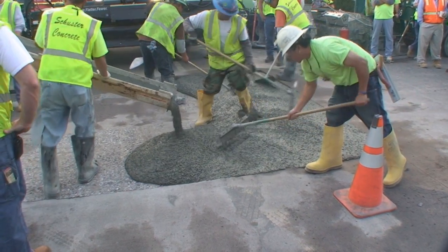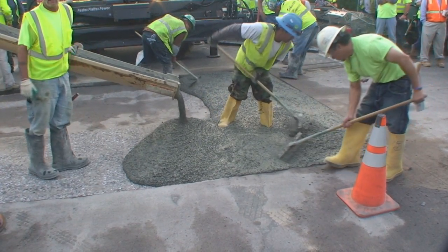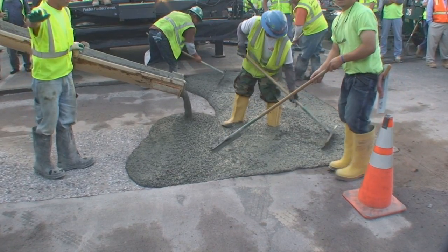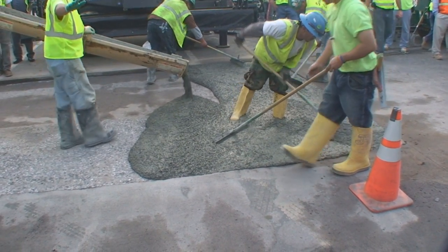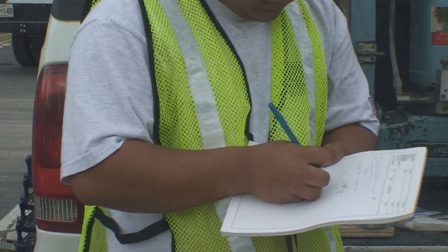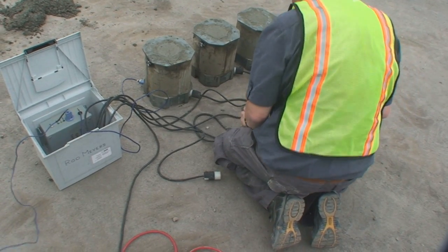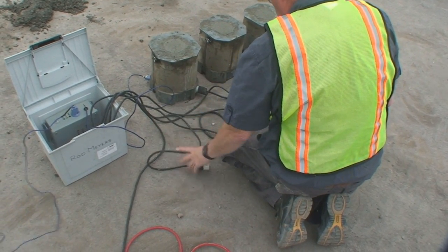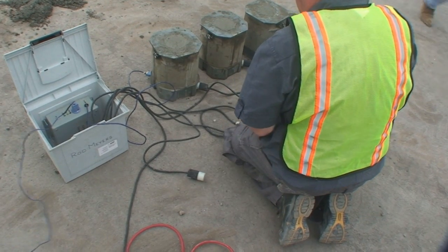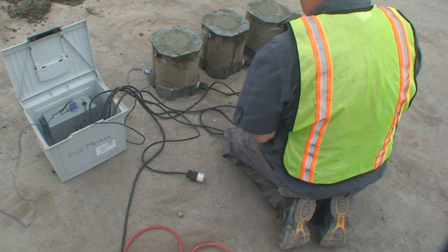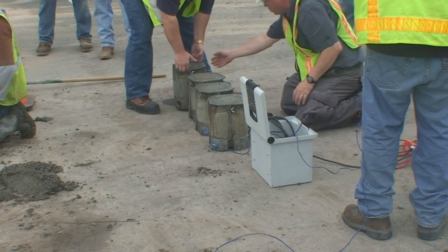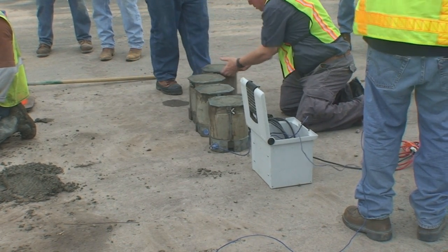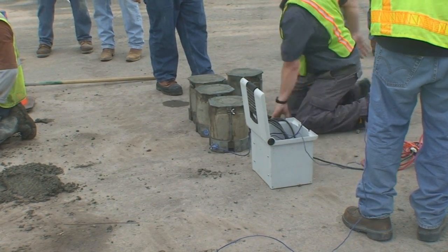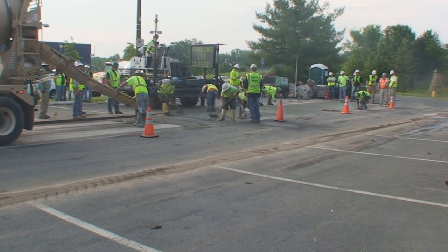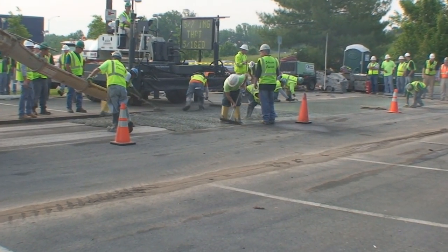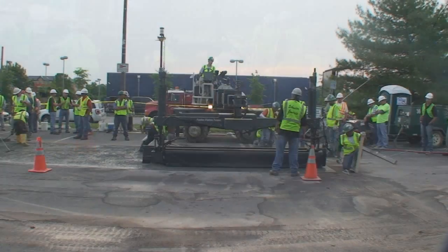The concrete mix used was a test of a new performance-based patch mix for the SHA, with a design strength of 2,000 PSI in 6 hours and an ultimate 28-day strength of 4,000 PSI. The mix contained admixtures to achieve this high strength in a short time and synthetic macrofibers for cracking control with no need for any additional reinforcement. The performance mix was designed by the Maryland Ready Mix Concrete Association's Technical Committee and the State Highway Administration.